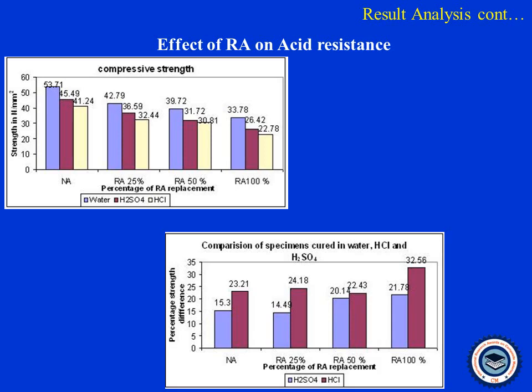The pH value is also one of the important factors to influence the rate of corrosion. The normal pH value for the concrete to passivate the reinforcement against corrosion is 12. If the value comes below 9, the carbonation of concrete takes place and the corrosion also gets initiated. So the general pH value of the solution and the level of inducing corrosion in concrete was tested, and from the results it was very clear that the effect of H2SO4 is much higher than the HCl. The replacement of recycled aggregate decreased the resistance against corrosion in all kinds of solutions. So finally we found that the possibility of corrosion is high in the 100% replacement of recycled aggregate concrete when it is subjected to H2SO4.